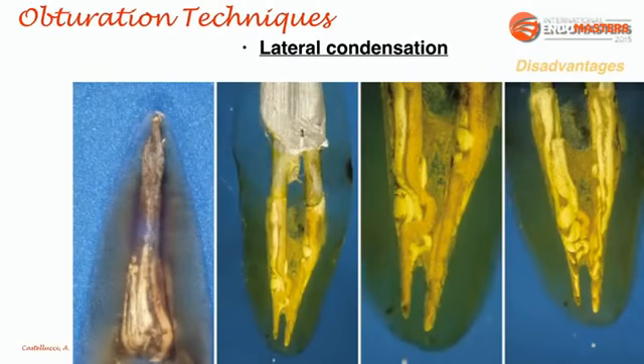Being lateral condensation a cold technique, the gutta percha cones never merge into a compact mass, but the technique will always yield an obturation consisting of a number of gutta percha cones separated by a greater or lesser amount of sealer, depending on the dentist's ability. The problem with the technique is that it is easily abused by the clinician. While the spreader negotiates the space through the length of the obturation, a considerable amount of force occurs and there is an important risk of fracture.